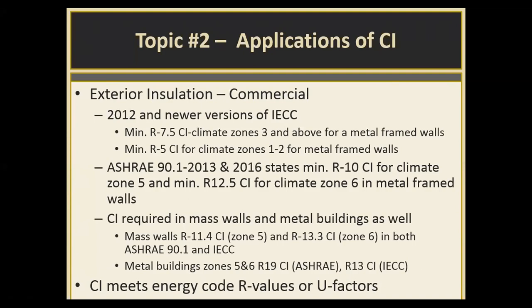So one of the big adaptations with continuous insulation is in steel frame buildings where the code is requiring a minimum of 7.5 continuous insulation R value outside of the framing members in climate zones 3 and above. And even in climate zones 1 and 2, there's a minimum of R5 required. As you go further north in steel framed walls, you start seeing those increase even to 12.5 or 10, depending upon which climate zone you're looking at, if they're using the ASHRAE 90.1 standard as the measuring stick.